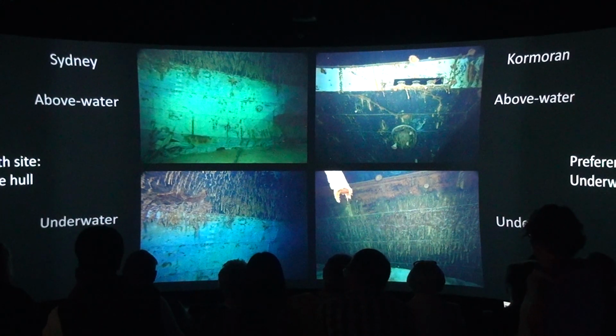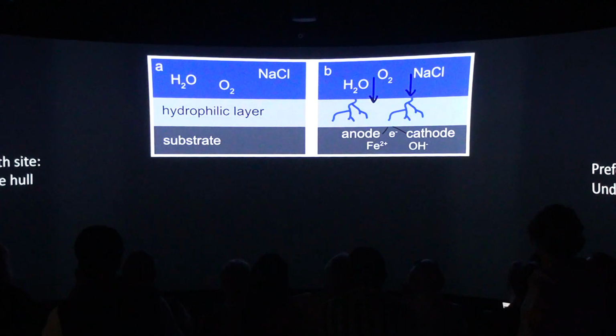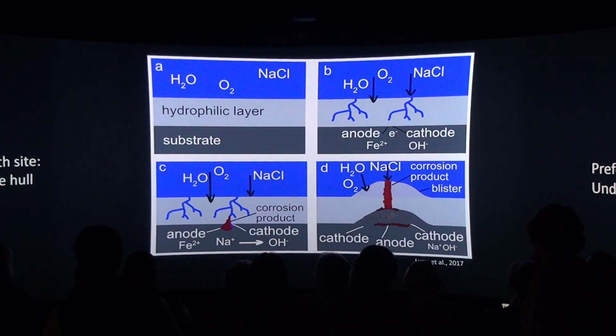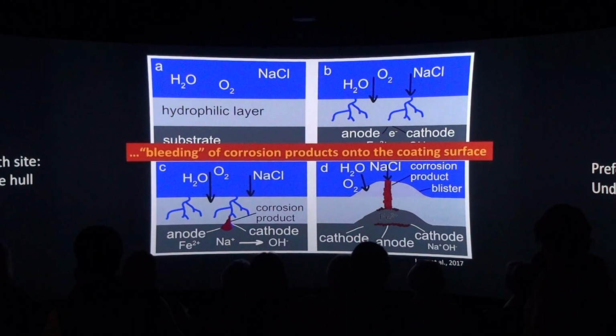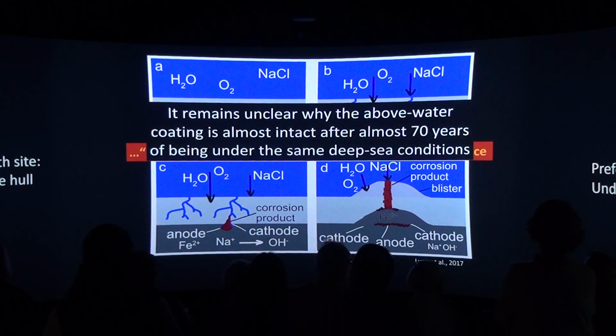So when the ships just sunk, all this food was consumed in a really short period of time. So another possibility was that since it was an underwater portion of the hull, the coating was soaked in water. And once they sunk, they reached this extremely high pressure all of a sudden, and these little pores were filled with water, but the water hadn't reached the metal part underneath the coating. So when it reached this high pressure, the water was pushed up to the metal, and then it started the corrosion process. And this corrosion process then started bleeding the corrosion products onto the surface. And that is what we now see as the rusticles developing in the underwater portion of the hull. We still don't know why the above water coating is almost intact after 70 years of being under the same deep sea conditions. So if you have any ideas, please.